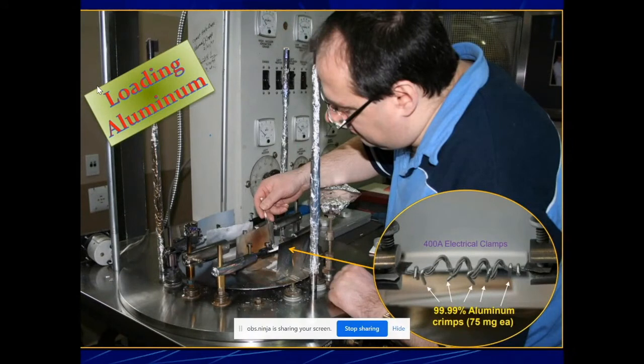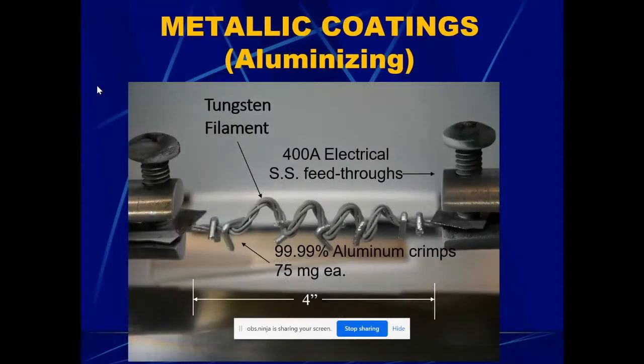So we use a tungsten filament for evaporating aluminum, and it basically looks like the same kind of filament that would be in an incandescent light bulb. What we do is hang off pure aluminum crimps, about eight of these or so, 70 to 75 milligrams each. Everything's pre-weighed, so we get exactly the same coating thickness all the time. A lot of current goes through this filament, about 400 amps.